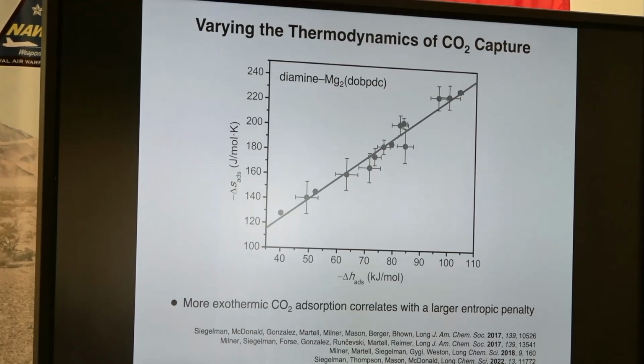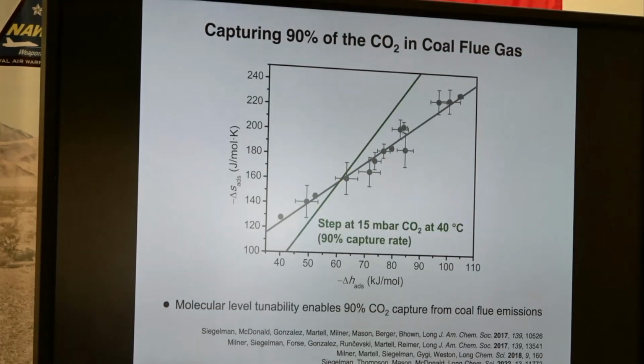But as you go to stronger and stronger enthalpy contributions to the driving force, you're making more and more tightly held chains, and you're paying a larger and larger entropy penalty. And so we're falling along this gray master line. And it means you can choose a diamine to create an adsorbent customized to a particular gas mixture.